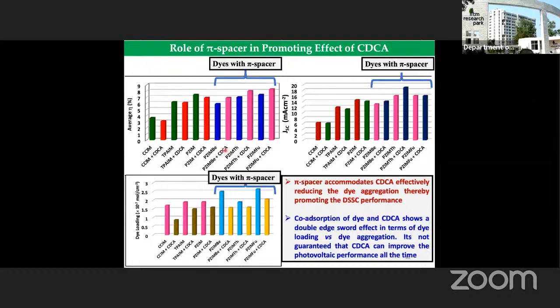But when she includes a spacer like benzene, thiophene, or furan, and then adds CDCA, there is an increment in the performance. Why is it increasing? You can see here JSC has gone up, VOC has gone up. Also, your dye loading is not as low as this guy here, but there is a decrease in dye loading always. But it seems the gain we get due to anti-aggregation is better than the loss we have due to dye loading reduction.